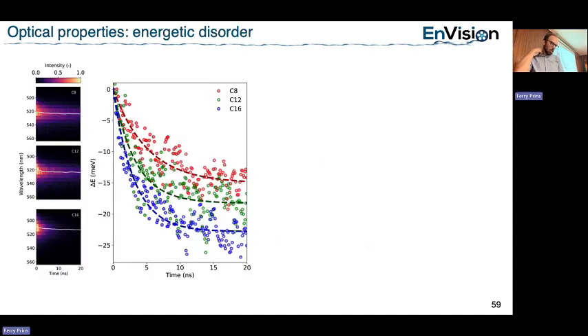We can see this also in these time-resolved spectroscopy measurements, where we take the spectrum as a function of time. In all three of them, we see this redshift. If you make a film, the particles are moving downwards in energy, but the redshift is much larger for the C16.